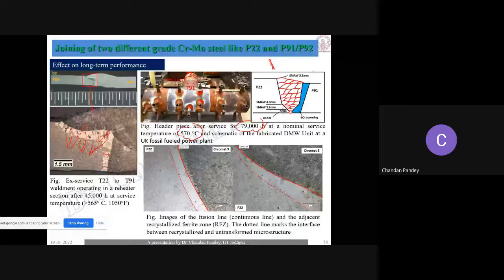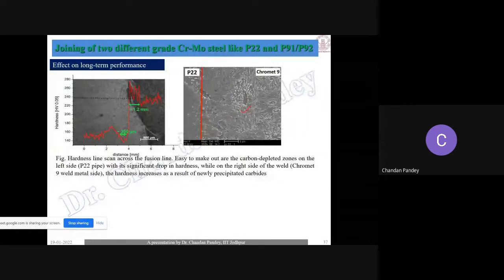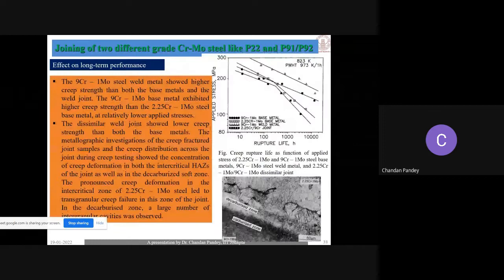Now, if you talk about the service condition, that is about your long-term service condition. There are two types of service we consider, where the material is subjected to high temperature. In that case, the thermal stress will be something. After that, during cooling, it is subjected to room temperature. At that point, the overall thermal stress will be different. So that thermal stress comes due to the application, which is related with the creep rupture strength, and others also. So during the creep condition, during the high temperature and loading condition of that welded joint,